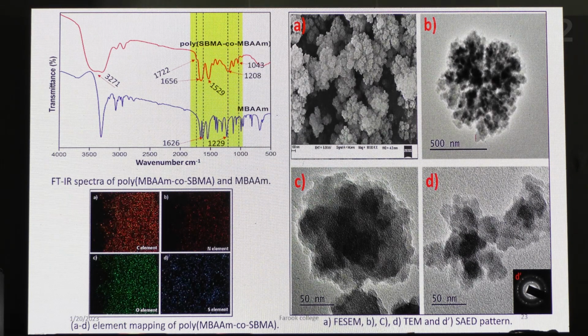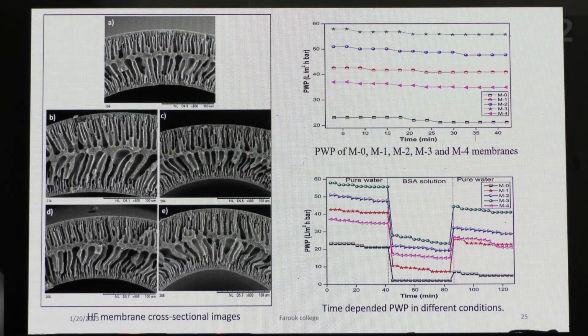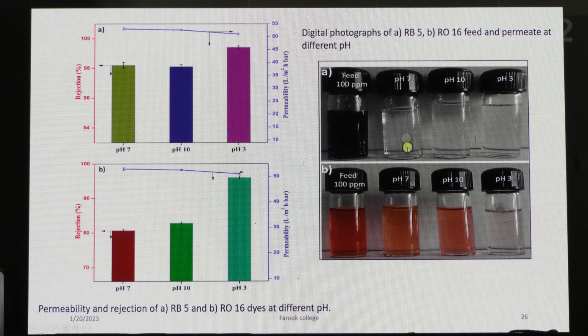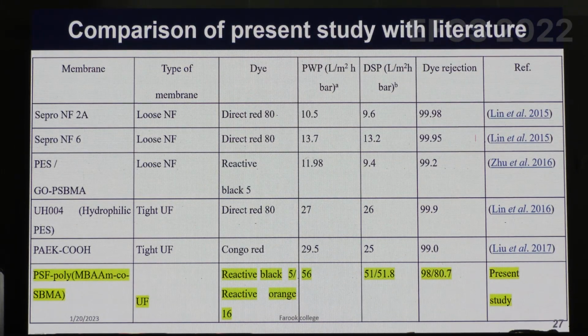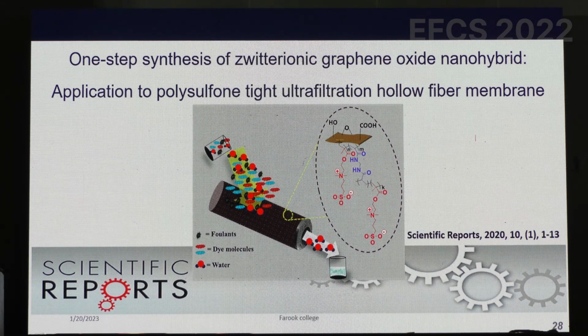And of course, different characterizations were done to confirm the formation of those zwitterionic nanoparticles. And you can see the beautifully arranged finger-like projections, which are nothing but the microvoids in the hollow fiber membranes, and the presence of these zwitterionic additives has significantly improved the performance. You can see the results in the next one. These are two different types of dye solutions which I have prepared, one is RB5 and the other is RO16. In both cases, beyond 95-96% removal of the dye has been observed. And of course, we have also compared with other already reported as well as commercial membranes, and our materials were found to be more superior.